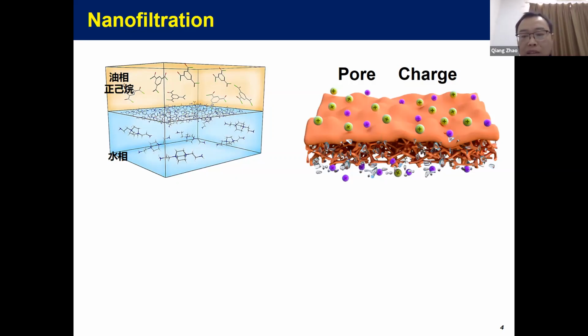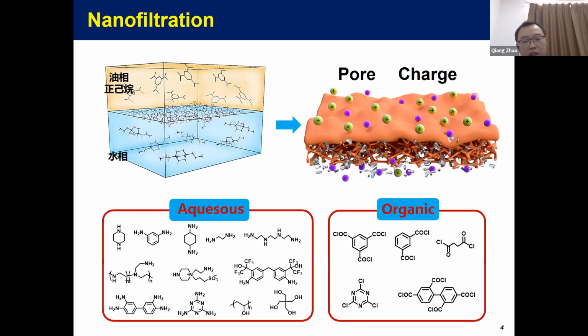And the main mechanism for nanofiltration is a combination of pores, which is the size sieving, and the charge repulsion effect. So if we look into the chemical structure of the aqueous monomers and organic monomers, in particular the aqueous monomers, you will see that these monomers are basically neutral or weak electrolytes, which means containing amine groups. They are not strong cation or strong anion groups. So